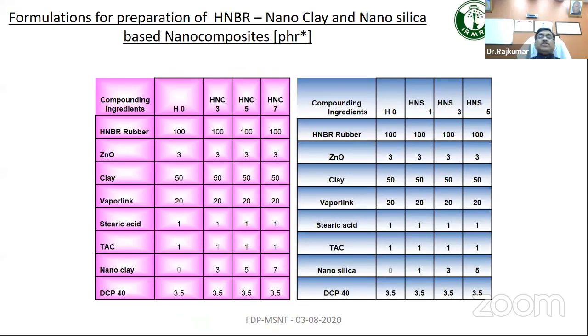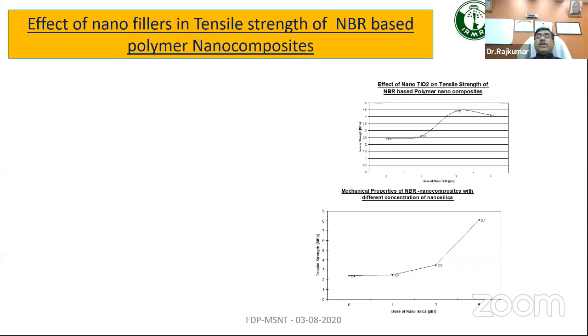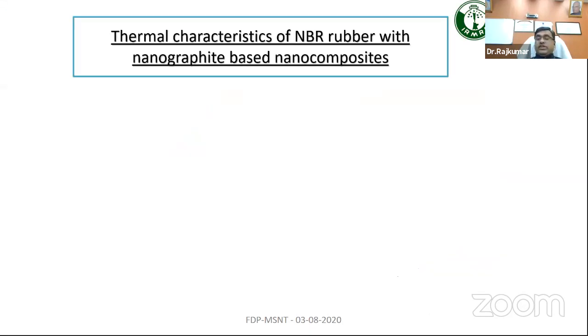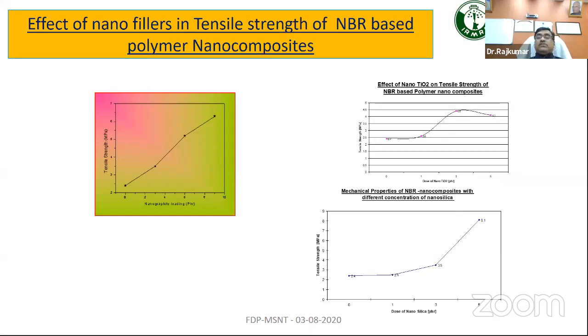So we tried to do some research on this, for example with nitrile rubber, HNBR, wherein we used nanoclay at 0, 3, 5 and 7 parts, and nanosilica at 0, 1, 3 and 5 parts, with the same DCP taken as the curing mechanism. Basically the strength is improving with these things.